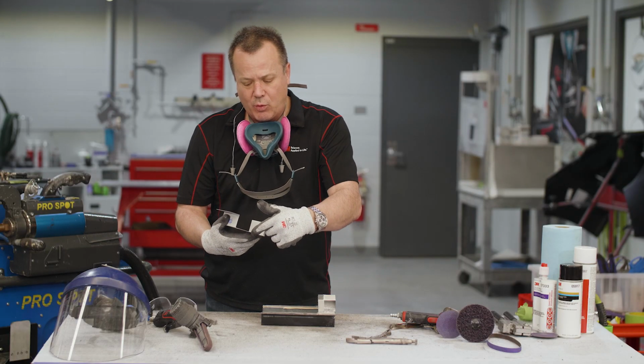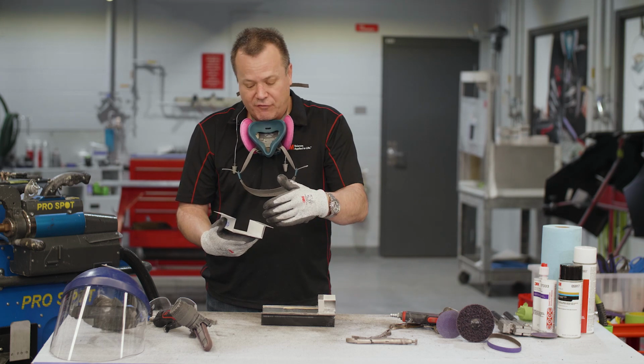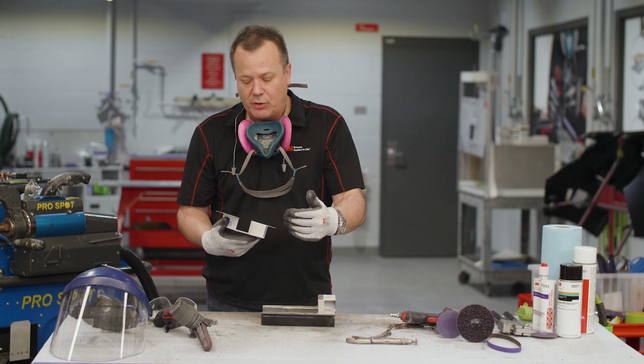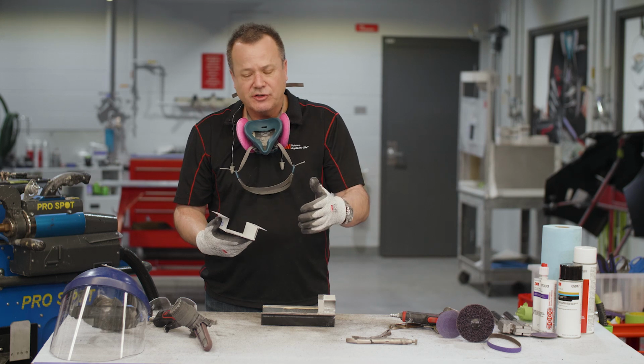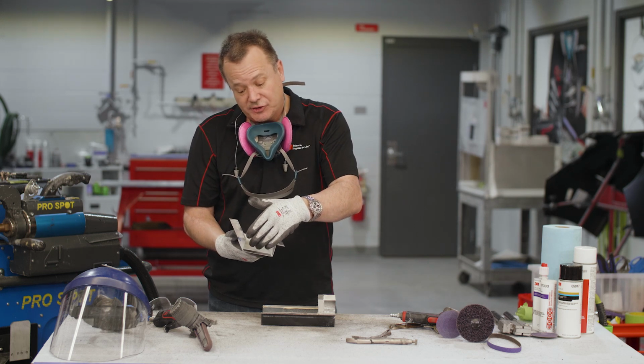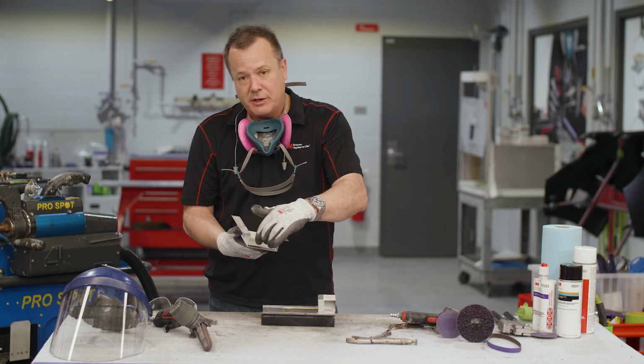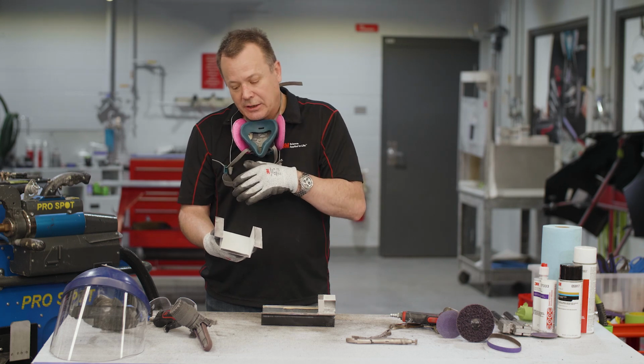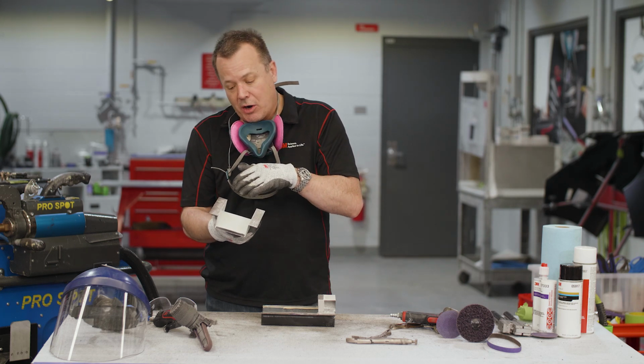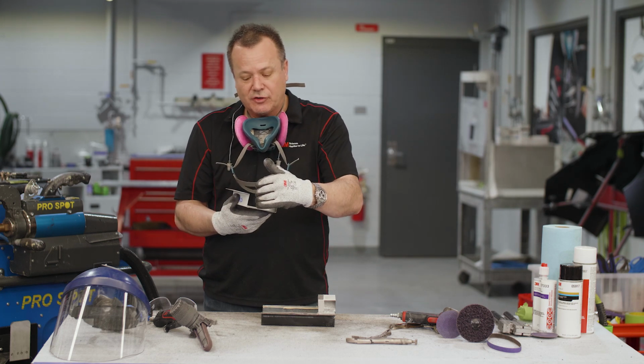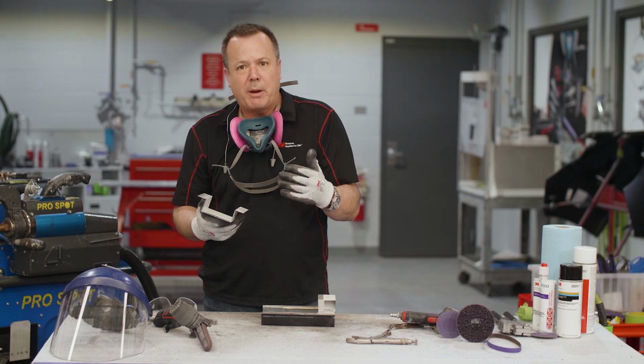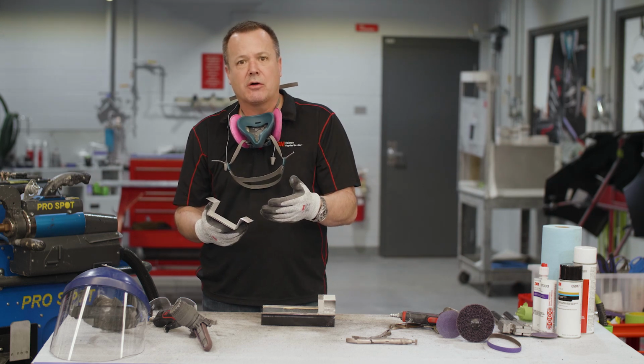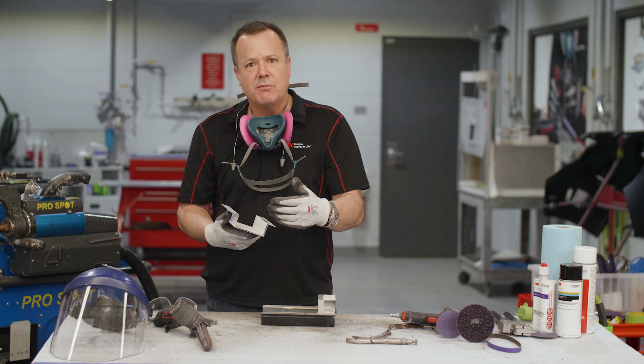When we start to MIG weld or mag weld on here, if we have paint in the way, we're going to get a poor quality weld. We're going to get all kinds of fumes, and the paint that's remaining here will also char and burn. Later, after the end of the repair, when we put cavity wax in here, if you spray it on charred, burnt paint and loose paint, it's going to fall off, and you're not going to have that corrosion protection. So we want to have nice clean metal there.